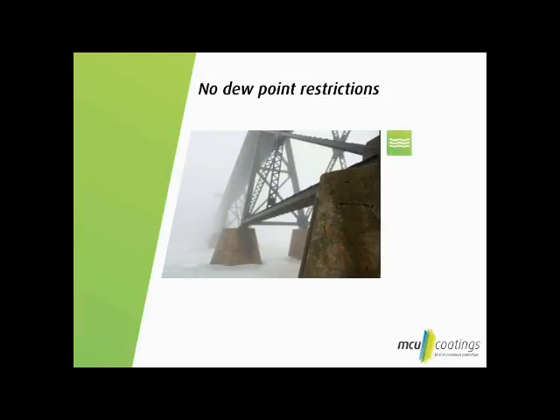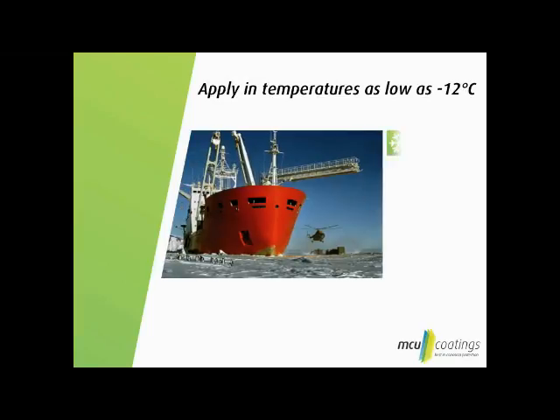MCU coatings have no dew point restrictions. All other high-performance coatings are unusable and have to sit on the shelf when the surface is within 3 degrees centigrade of the dew point. Nearly every outdoor painting project is delayed by this restriction. MCU coatings can be applied in temperatures as low as -12 degrees centigrade. Generally, all conventional high-performance coatings are restricted to application temperatures above 5 to 10 degrees centigrade.